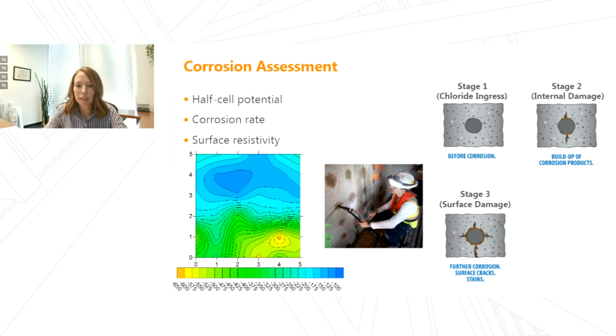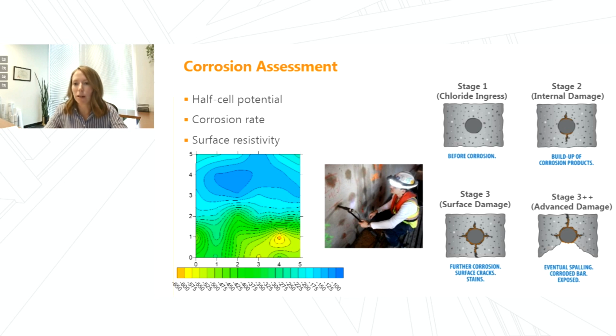And that's where this stage 3 level is, when you start to see cracks that have some of that rust staining on the surface. That's what we're seeing there around the stage 3. And then as that continues to advance, you get this stage 3 plus, where we'll say advanced damage. So here's where you have those larger spalls, you have exposed bar, you're starting to get severe section loss. And so the value of a corrosion assessment might not really be all that helpful when you're already at the stage 3++, because you have some exposed reinforcing, you can really determine the section loss.